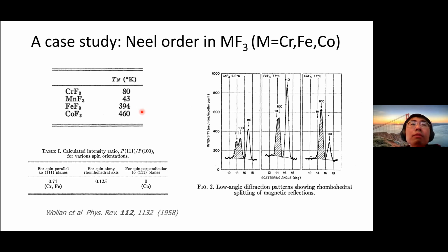For these three different compounds, there is a slight difference in the orientation of the spin. For example, if you look at chromium and iron, the spin is aligned along the 111 direction. On the other hand, in the case of cobalt, the spin is mostly aligned along the 100 direction. These are two different axes in the system, as I will comment on soon. This leads to slightly different properties between iron, chromium, and cobalt.